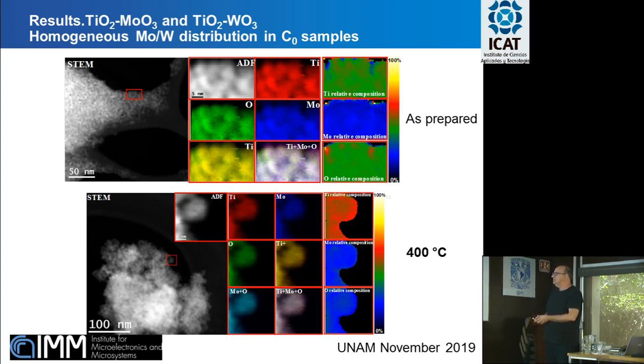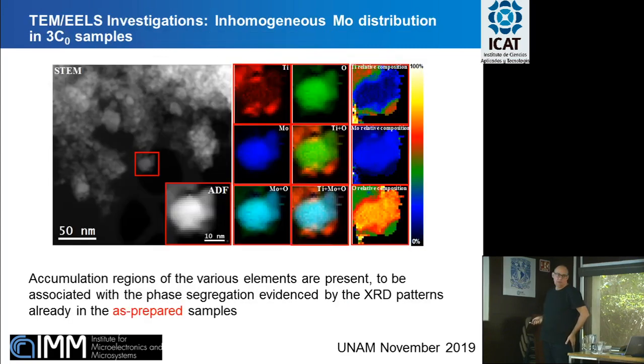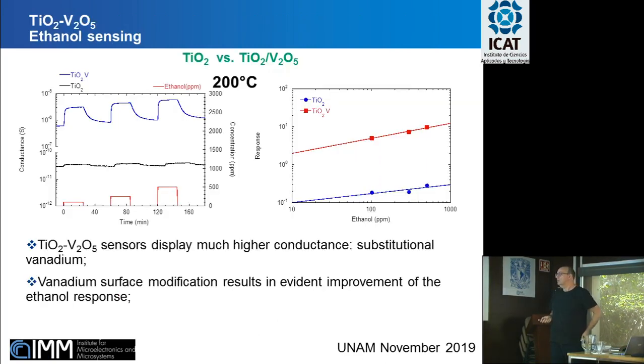We have our as-prepared materials, and after a treatment at 400 degrees C, we have clearly a homogeneous distribution of molybdenum oxide. But if we increase the molybdenum or tungsten concentration, we clearly see that there is phase segregation inside the sample. So this work also requires a very careful control of the concentration of the other oxide and a continuous monitoring by characterization techniques of the results that are coming out.